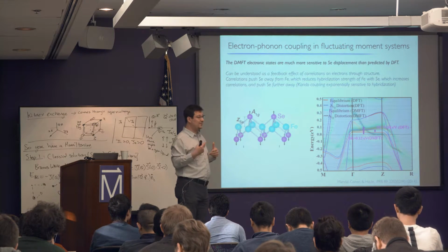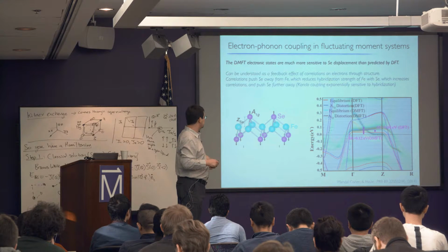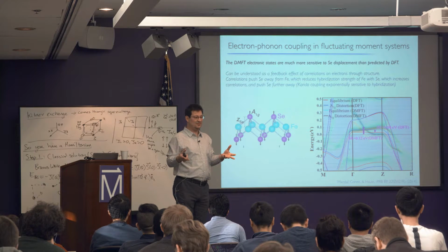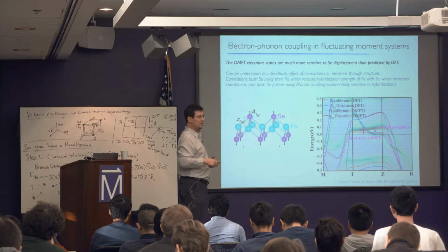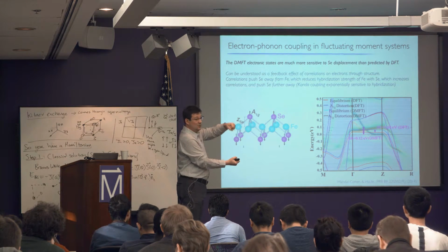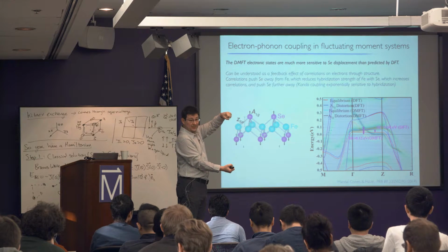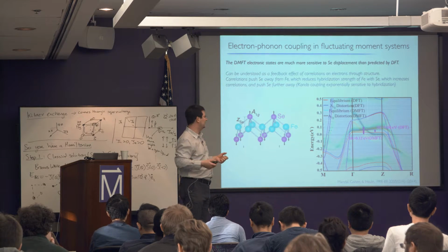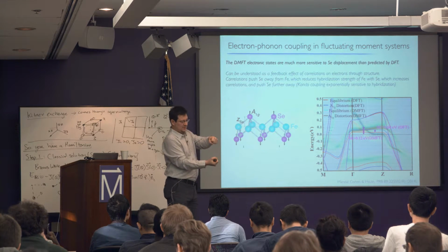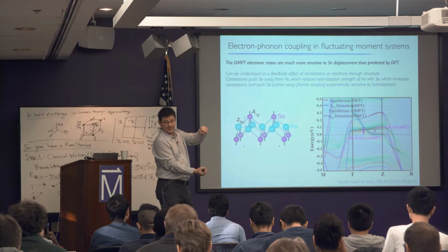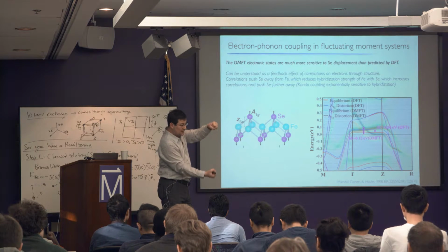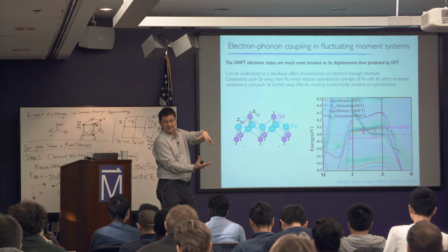Okay? And it's easy to understand why. So it's kind of a feedback effect of correlations. First, when you do a beyond-DFT method, you will immediately see that if iron becomes more correlated, then selenium will move away from iron. You can see this effect even in DFT plus U. In some sense it's taken into account even by Hartree. But of course with DMFT you can predict the selenium position much better. So in other words, selenium moves away from iron because of correlations, because iron starts to become bigger because electrons are more localized.